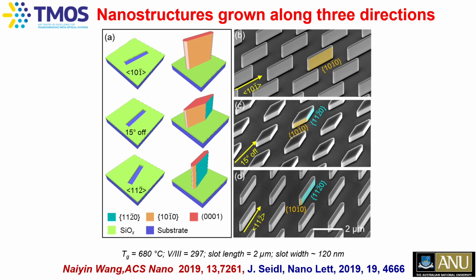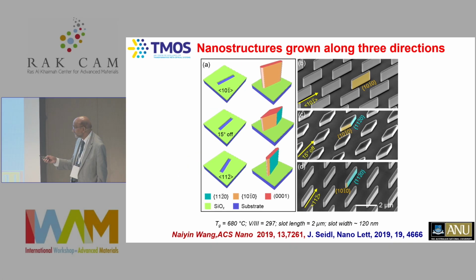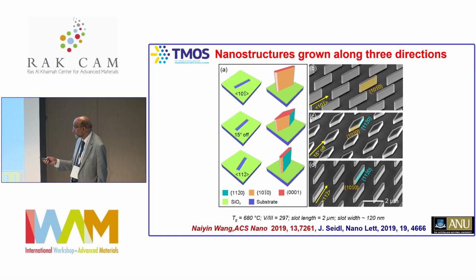So when you open this slot along a particular crystallographic orientation, and then put this one into the MOCVD reactor, and then increase it to temperatures like 680 degrees Celsius, introduce the gas needed for the growth of indium phosphide, you can get these beautiful membranes of indium phosphide with these sidewall facets, and this is determined by the crystallography of this particular structure. But if you open this slot along another crystallographic orientation, and again you can grow these membranes, but these membranes have got a different crystal facet.